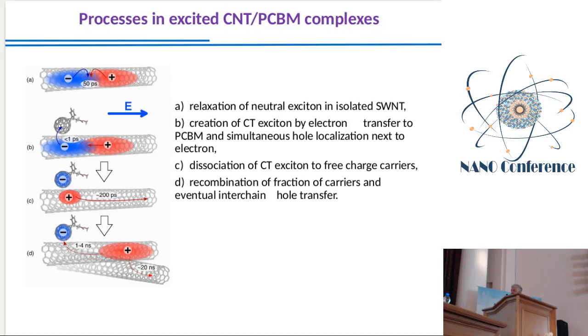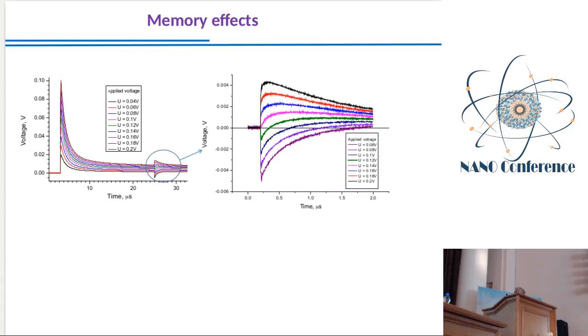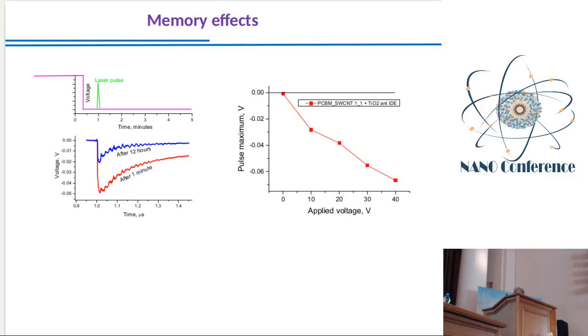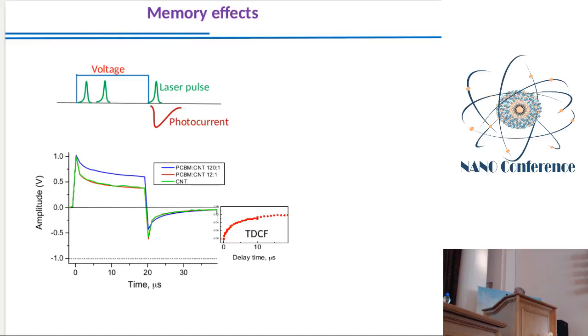Unfortunately I don't have time to talk about longer times, but a little bit. There are also some memory effects. When we apply an electric field, we can see photocurrent even after a long time, even after 12 hours, for example. This electric field initially is stronger, later on decays, and here we see the decay of this electric field on a 20 microsecond time scale, which is very similar to the results obtained by time delayed collection field. So here we observe very, very deeply trapped charge carriers.